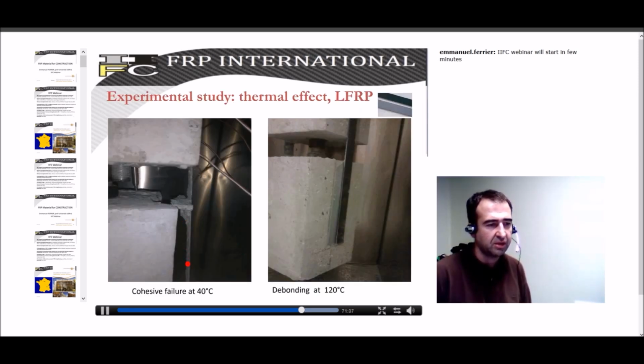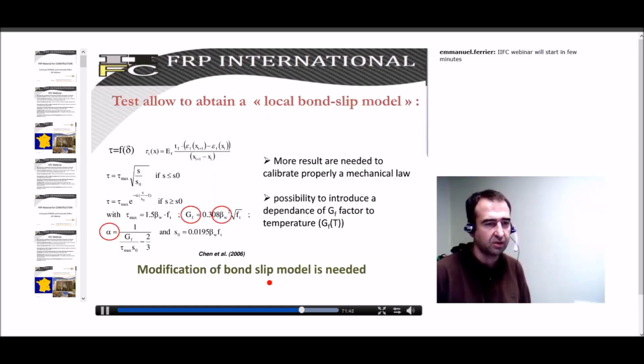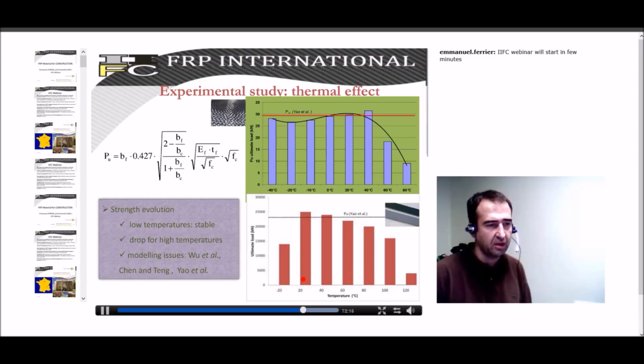Same observation with laminate: cohesive failure, and then non-cohesive failure at 120 Celsius degrees. So the main parameters that should be modified to consider the temperature effect are the GF value, the value of beta depending on the bonding length, and also the factor alpha here. This work is quite new for us, and now we are working to build a new model to introduce the temperature effect in the bonding.